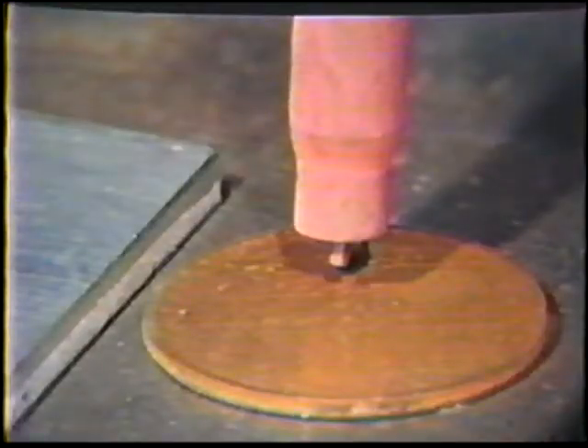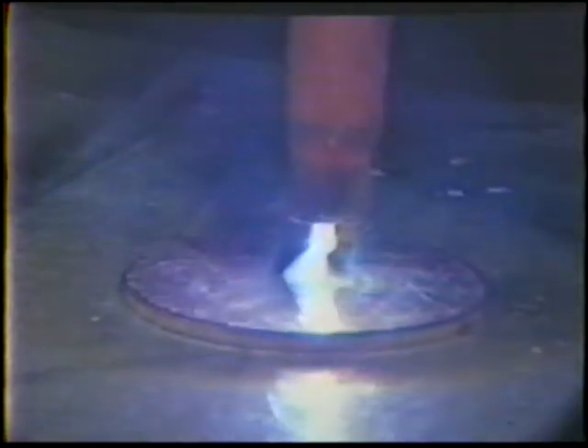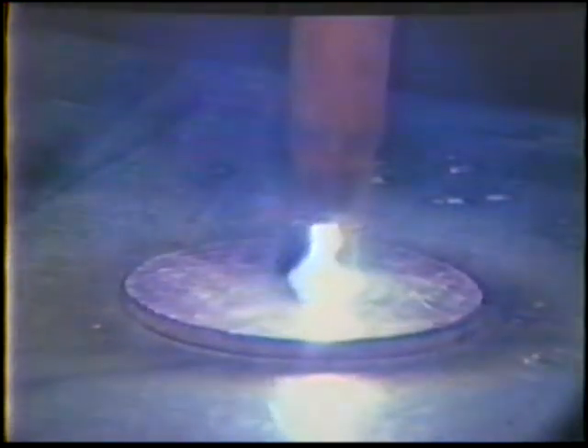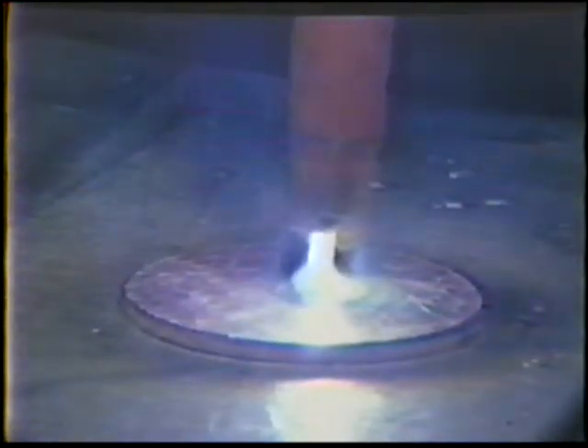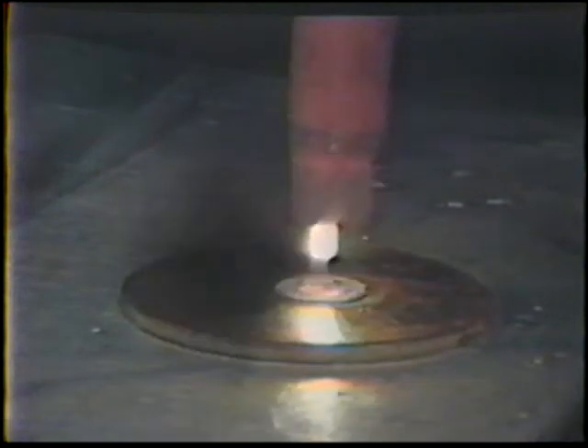The torch should be positioned at a 90-degree angle to the copper plate, with an arc length no greater than 1/8 inch. Press the foot rheostat all the way down for maximum current. Do not touch the tungsten to the copper. As soon as the ball is produced at the tip, release the foot pedal.